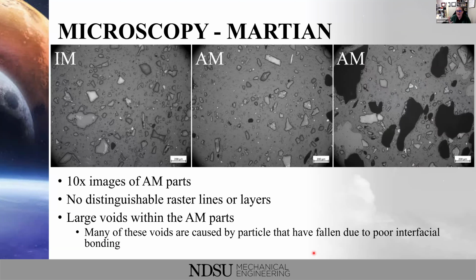So we did do some microscopy images, just to look at these parts and think about, what are we looking at? Are we actually getting voids, that type of thing? Are the voids themselves from particles that have fallen out? Are they voids just within the part? Do they come from between raster lines, between layer-to-layer adhesion, where those voids might come from?